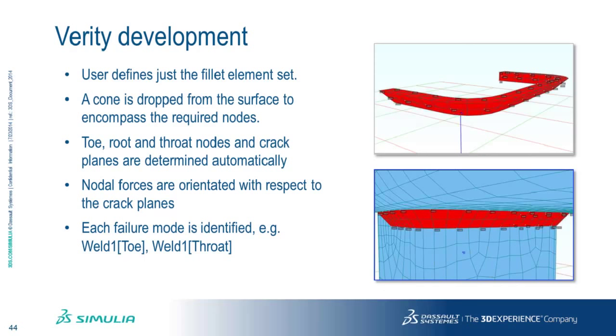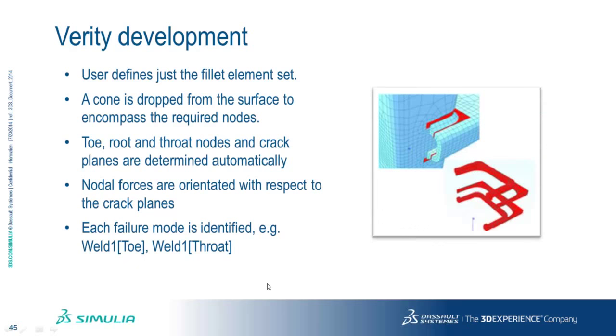creates separate element groups for each of the possible cracking modes. It automatically aligns the forces perpendicular to each of those different cracking modes, and it calculates fatigue lives for each of those different cracking modes as well. So this is a highly automated process. It makes the Verity method much easier to use than it was before.